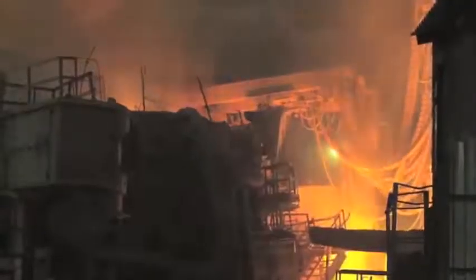And it's loud. Very, very loud. The rods circulate, or arc, up to 115 million watts of electricity to melt the scrap at a temperature reaching 3,000 degrees Fahrenheit. The power is on for about 35 minutes to complete the melting of each heat, which is a good reason why our monthly electric bill is about 7 to 8 million dollars.